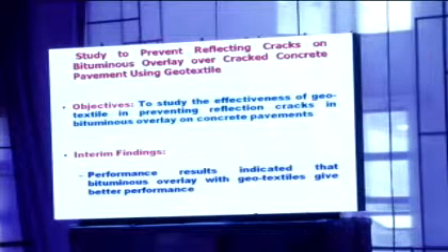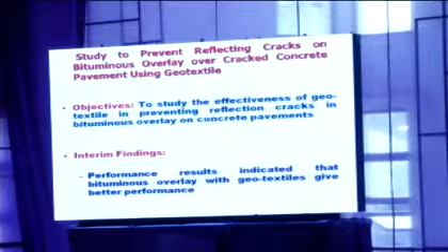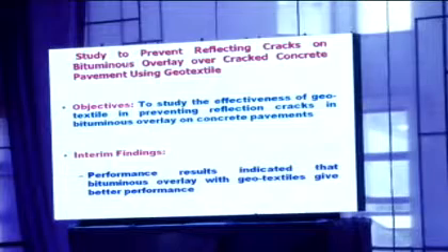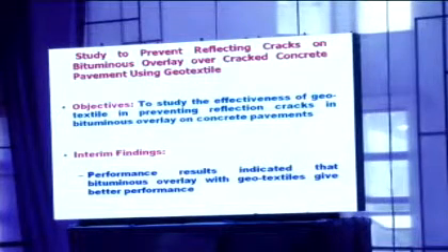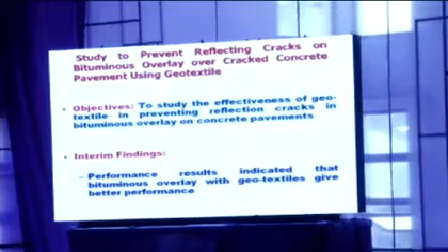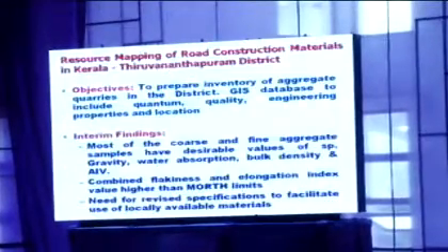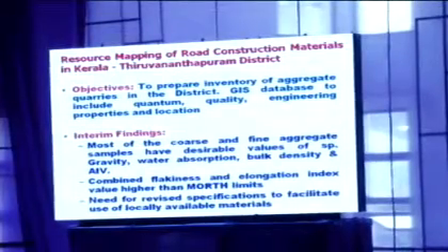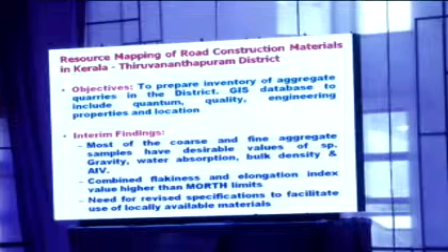The next project reported is a study to prevent reflection cracking on bituminous overlays over cracked concrete pavement using geotextile. Whenever a bituminous overlay is placed over an existing concrete surface, the joints are reflected into the overlay. Geotextile has been used to minimize those reflection cracks under this project, and it has been observed that a bituminous overlay with geotextile gives better performance, and mitigates the occurrence of reflection cracking in bituminous layers whenever placed over existing concrete pavements.